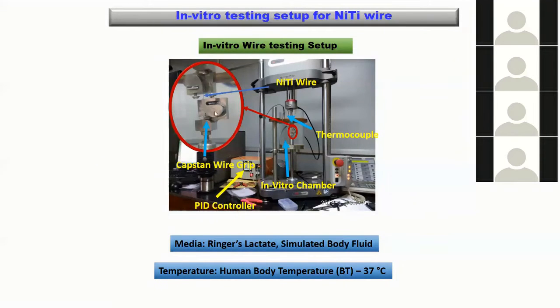So what we did is, we have the wire being tested in a UTM. This is a universal testing machine for testing the tensile, compression and fatigue failure of a material. Okay, the wire is hung here using a specialized grip. And this is a chamber, a biochamber, in which we put different kinds of liquid of our interest. So we put either Ringer's lactate or the simulated body fluid. And most importantly, we maintain the temperature of this fluid at human body temperature. That means the testing is being done at the human body temperature while the specimen is immersed in the fluid of concern. Okay, so it's 37 degrees centigrade.